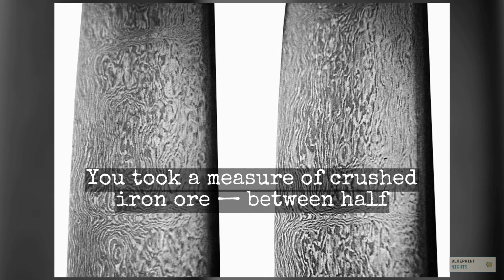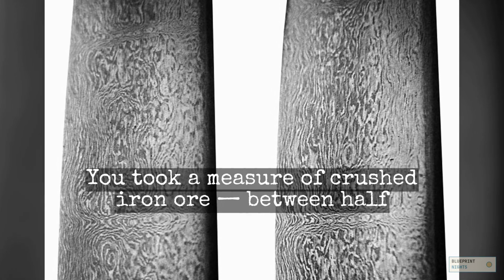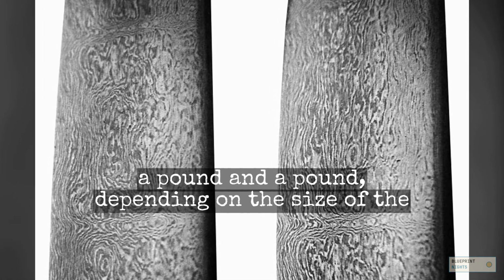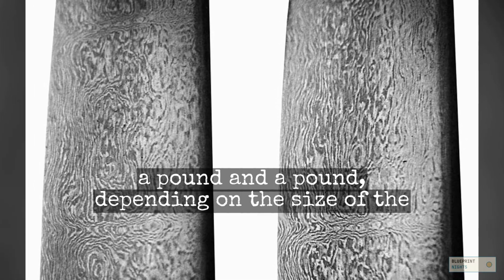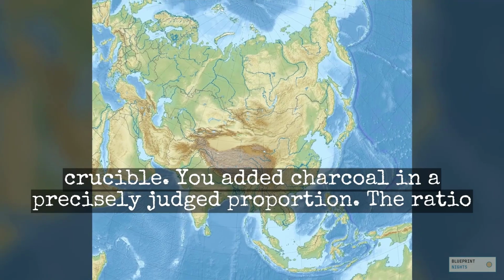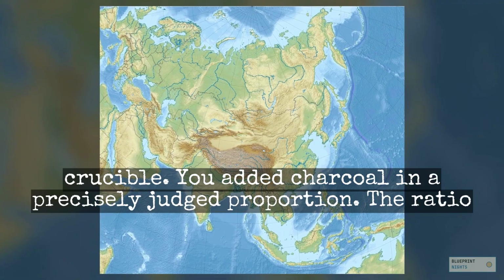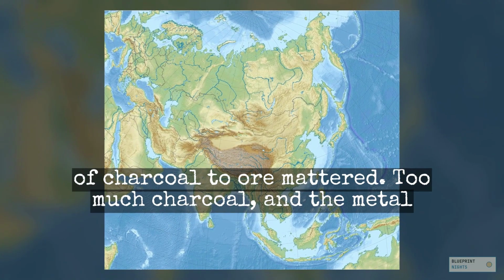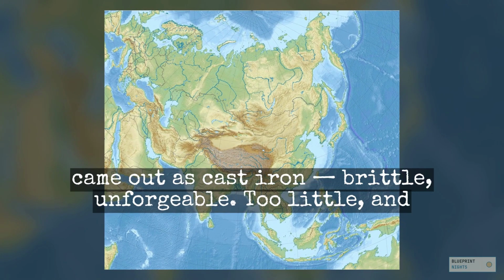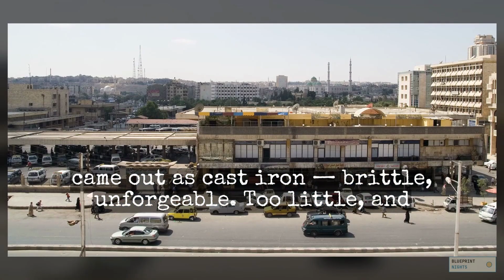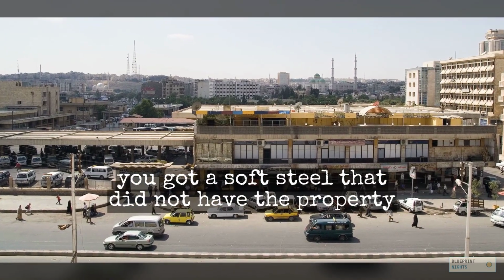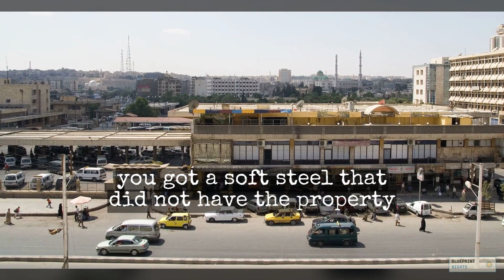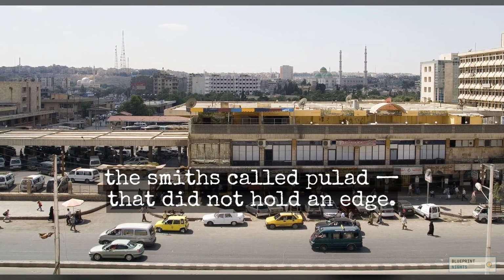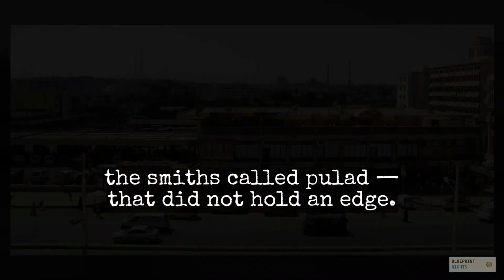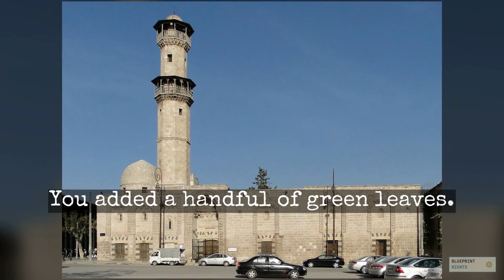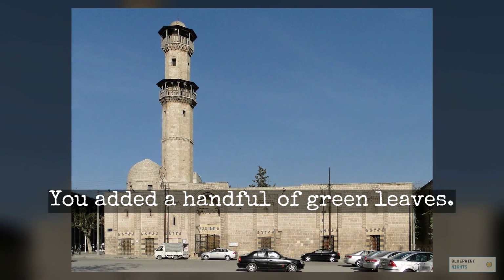You took a measure of crushed iron ore, between half a pound and a pound, depending on the size of the crucible. You added charcoal in a precisely judged proportion. The ratio of charcoal to ore mattered. Too much charcoal, and the metal came out as cast iron, brittle, unforgeable. Too little, and you got a soft steel that did not have the property the smiths called pulad, that did not hold an edge. You added a handful of green leaves.